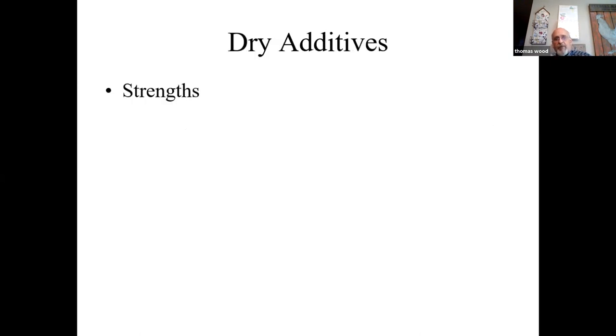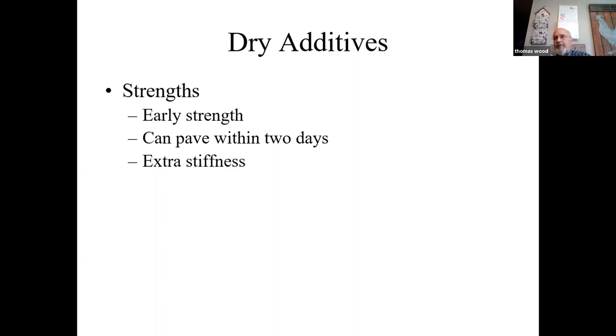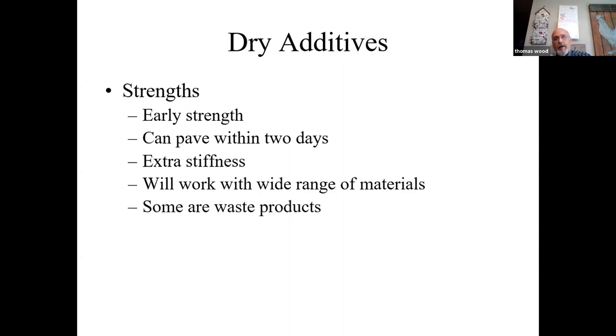Dry additives, strength, early strength. If you use cement, fly ash, or lime, you can get phenomenal strengths early. Pave in a day or two. Extra stiffness will work with a wide range of materials. Some of the materials that we're using were waste products, like when fly ash used to be available. But now most of the fly ash goes to the concrete industry, which uses it.